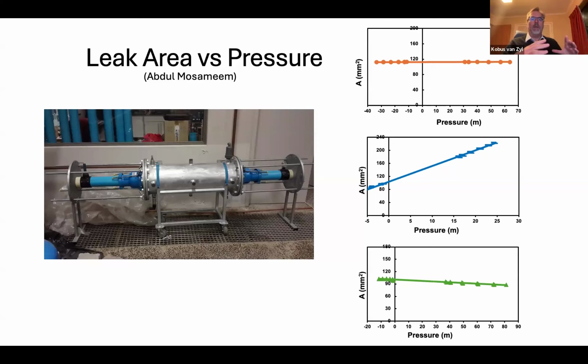Then when we look at the area of a crack or a leak, we also know that that area varies with pressure, and we know that it varies linearly with pressure. I'll come back to the picture in a moment, but this diagram shows the area of a round hole with pressure. And you can see round holes are completely stable. They don't change, so they act like orifices. The same behavior occurs with small diameter steel pipe or metal pipes. These are longitudinal cracks, and they vary greatly with pressure. The cracks open up if you increase the pressure, and so the area increases.